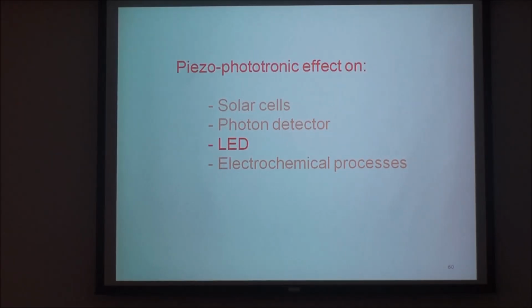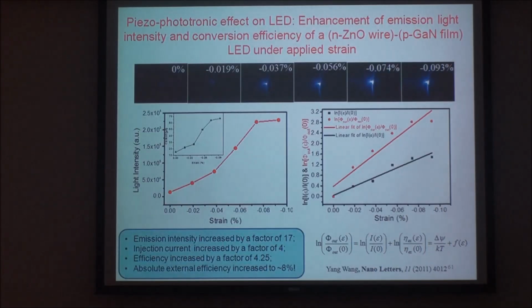The second example I give you is the LED. I skip the electrochemical process, although this also can enhance electrochemical processes. Let's look at the LED. LED is charge recombination. If you have P-type gallium nitride, you put N-type zinc oxide on top of that, and you apply the proper strain here, and look at the emission light. Without the piezotronic effect versus with the piezotronic effect, the emission intensity has a factor of 17. The absolute efficiency has a factor of 4.25. Not 4%, it's 400%. So this is a gigantic enhancement.